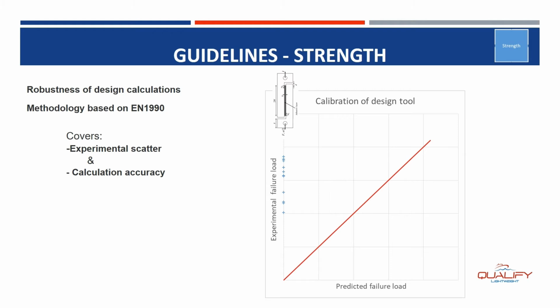So let's think we have an adhesive bonding assembly. We build a test setup and we break it experimentally so that we get an experimental failure load with the scattering, which defines the dispersion associated to the material, to the design, and to the process. Then we can make a calculation for this assembly, for the same setup as the test setup, and this calculation will predict one failure load so that we can plot the predicted failure load against the experimental failure load.